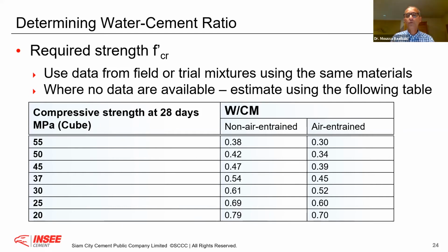Therefore, if I am producing a concrete with water cement ratio above 0.65, you will see in the EN 206, these are all what you call lean concrete. These are not for structural concrete, not for concrete with reinforcement, because the maximum you can go is 0.65. Therefore, as soon as in the bad market, a concrete gang leader or these people who produce the mason concrete add water and go to 0.7, you test, you have 22 megapascal, you are happy, but you should not be happy.